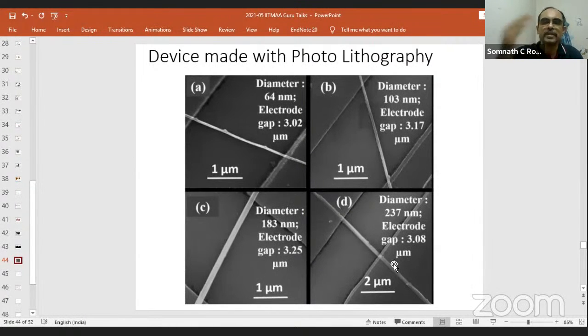We have done the diameter dependent charge transport, where we took copper oxide nanowires of different diameters and measured the current voltage characteristics, and we found a markedly different behavior. Of course, here also, as I said, there is a role played by the impurity phase. What you see is CuO, but there are traces of Cu2O inside, which also affects the charge transport characteristics.